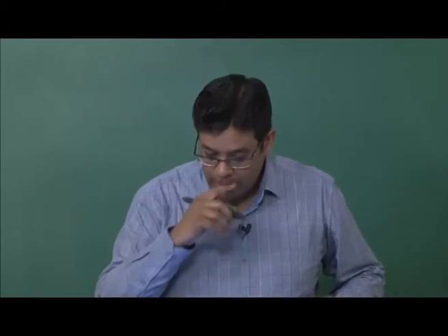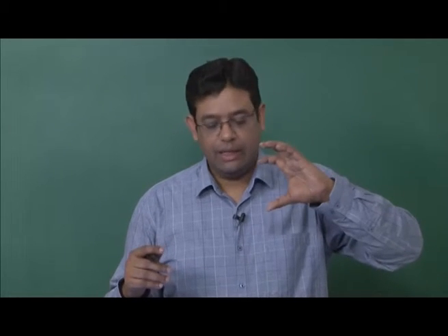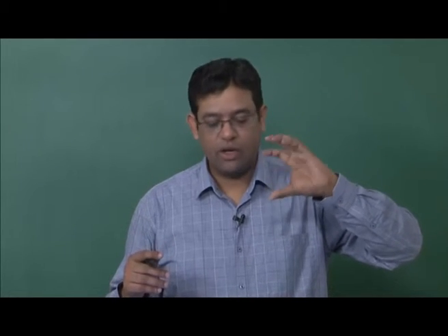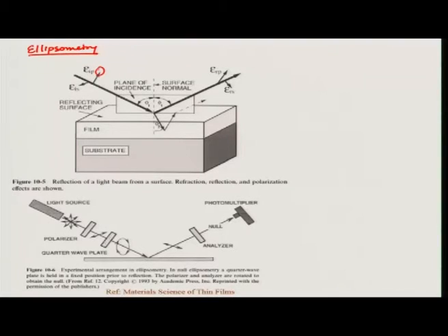A linearly polarized, circularly polarized or non-polarized light will have both perpendicular and parallel components of the electric field which are incident onto the surface. And when it is reflected, their ratio of perpendicular and in-plane electric fields will change. And their phase will also change differently.